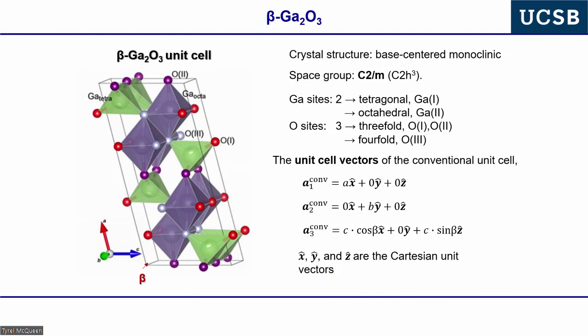Okay, for those of you, and probably most of you are not familiar with beta gallium oxide, quite often people say, well, what's the crystal structure of beta gallium oxide? And the answer is the beta gallia structure, okay? So it's a unique structure. It's not a simple deviation from any other crystal structure. Half of the gallium cations are in tetrahedral sites, shown with the green tetrahedrons here, and half of the gallium cations are in octahedral sites. So there are two unique gallium sites in the crystal structure. It's monoclinic. It's very monoclinic. It has a short b axis, a fairly large c axis, and a huge a axis. I'll show the lattice constants in the next slide. And then it has 3 unique oxygen sites. And then there are 2 primitive unit cells in this